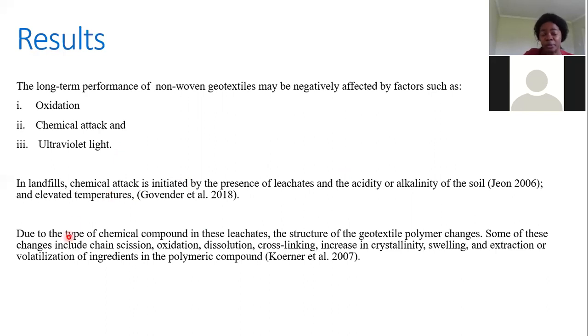But because leachates are chemical compounds that are very aggressive, they have the ability to interact with the polymer of the geotextiles and change its nature. Some of those changes can include chain scission, cross-linking, an increase or even a decrease in crystallinity, swelling of the polymer, and an extraction of most of the components that were used in producing this polymer.